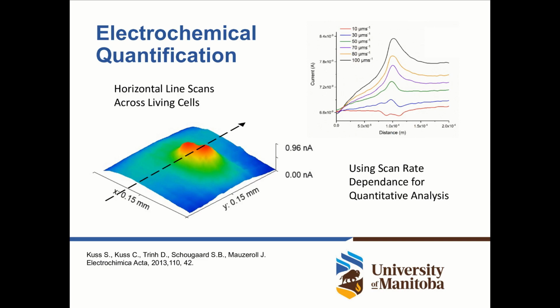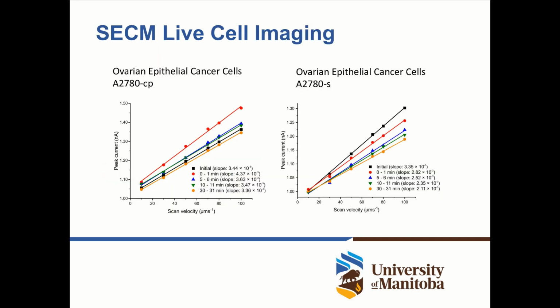with increasing scan velocity. This is because when our electrode crosses across a cell, we basically squeeze the fluid in between the cell and the electrode, and the faster we do so, the higher the accumulation of electroactive species in between the electrode and the cell. I will come back to that point in a minute. But what we obtain is a profile of line scans that increases its current with increasing velocity. Then we can select these peak currents, the highest point of these line scans, and plot them as a function of scan velocity. On the left-hand side, you see the carboplatin-resistant cells, presenting the peak current as a function of scan velocity, and we obtain a slope.